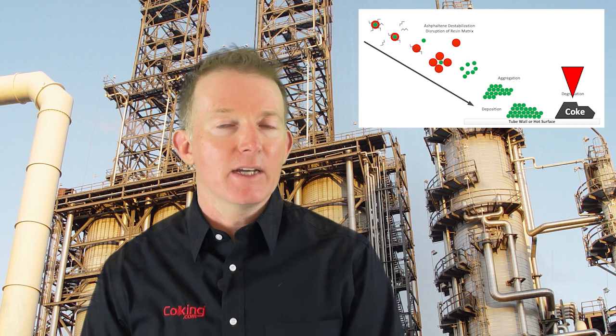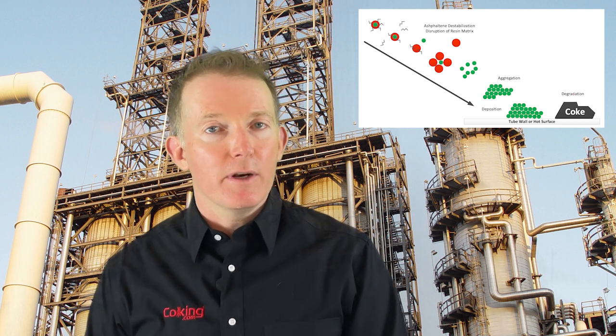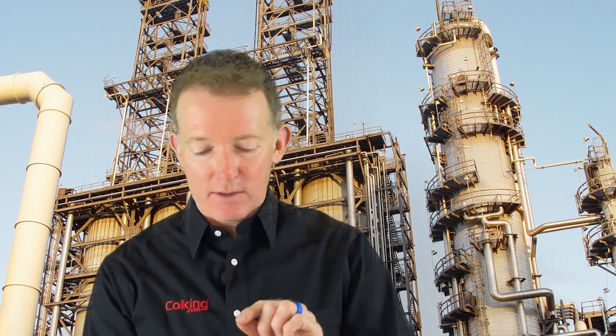They don't happen quickly, but if you remember that as a liquid is flowing across a surface, there's what's called the zero slip condition at the surface. That very thin boundary layer at that surface is basically stationary. So if the temperature is high enough for long enough time periods, you can basically make coke.